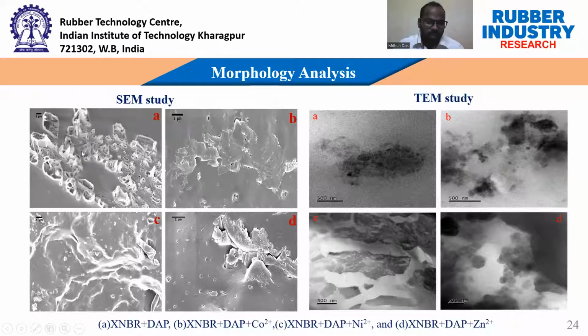From the SEM study, scanning electron microscope study, we have seen that in the only dye modified compound, the dye ligand forms solid particles uniformly dispersed through the rubber matrix, and this is the nickel modified compound. This is the XNBR dye plus cobalt modified compound, and this is the XNBR dye plus zinc modified compound. So we have seen that after addition of metal ion, the metal ligand complex forms, and the solid particles are uniformly dispersed throughout the rubber matrix. So from the SEM study, we understand that the uniform dispersion and the better coordination in the rubber matrix improve the mechanical properties and the healing efficiency.